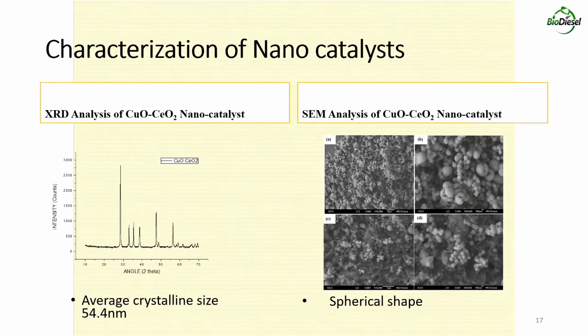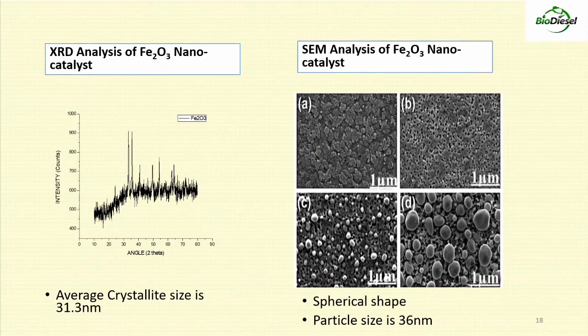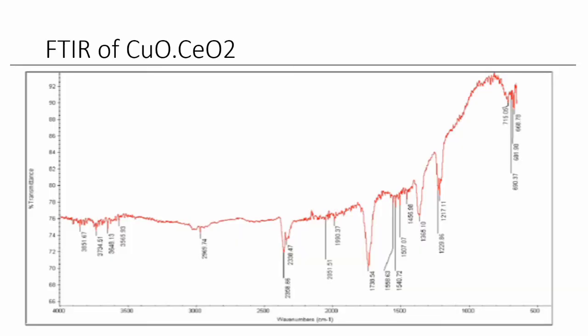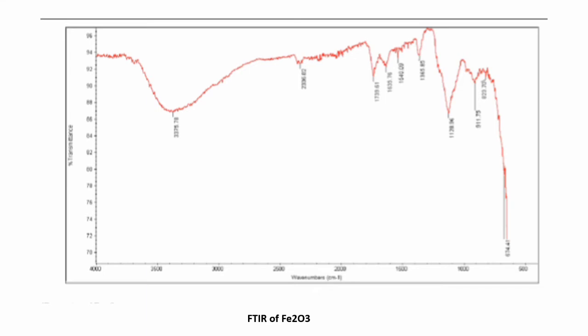The characterization of the nanocatalyst shows that the XRD results of the copper oxide and cerium oxide nanocatalyst give an average crystallite size of 54.4 nanometers, and it shows a spherical shape. For the iron oxide nanocatalyst, the average crystallite size was 31.3 nanometers, and the SEM results show that the particle size was 36 nanometers, and it is in spherical shape. FTIR of copper oxide, cerium oxide, and of iron oxide was also performed, and it confirms the presence.